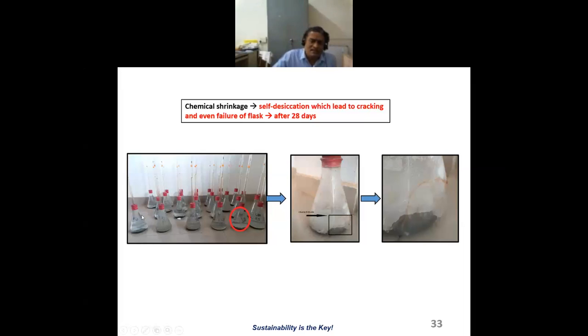You can see here, these are the flasks kept for the chemical shrinkage measurement for all the mixes. After 14 days, one of the beakers containing nanoparticles got broken. You can see there are larger cracks. So what do you have to do? The point here is we have to have adequate quality control practices. Your curing level should be absolutely proper when you deal with the nanosilica, otherwise you cannot avoid the shrinkage. So to avoid shrinkage, it is necessary to go for adequate quality control practices, nothing but giving more focus on the curing of the concrete or cementitious composite.